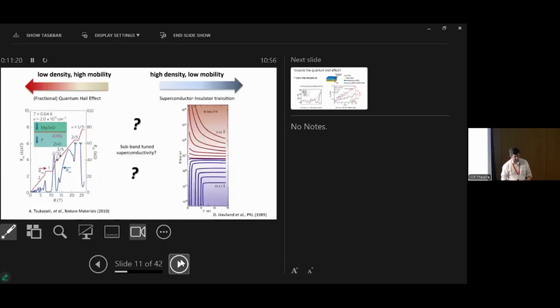So this is a kind of intermediate between traditional semiconductors. This is an example of zinc oxide, gallium arsenide, silicon, high mobility, low density semiconductors, which are typically not superconducting. That's one end of the spectrum. The other end of the spectrum are materials which are typically superconducting. They might have high electron density, but very low mobility. There's lots of scattering. And so we're somewhere in between here, and that transition is really interesting.